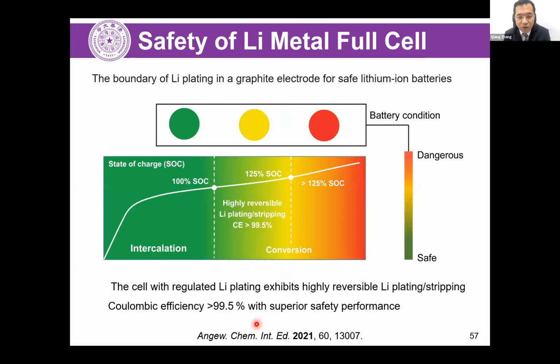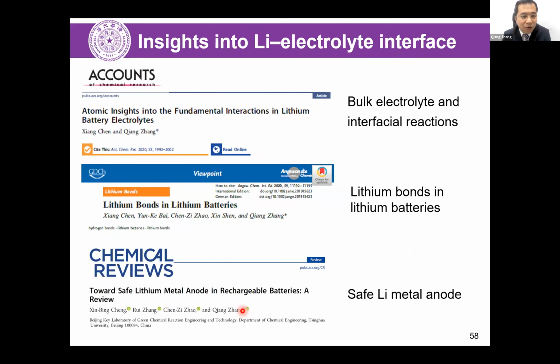It is found that uniform deposition of lithium metal anodes is a necessary step. And we also found that an addition of 25% overcharge is still safe in most cases, especially once we guarantee the Coulombic efficiency is more than 99.5%. Superior safety performance can be available in this case. So this provides the foundation for the addition of lithium at the initial stage, which can help lithium metal anodes achieve a long cycle life.